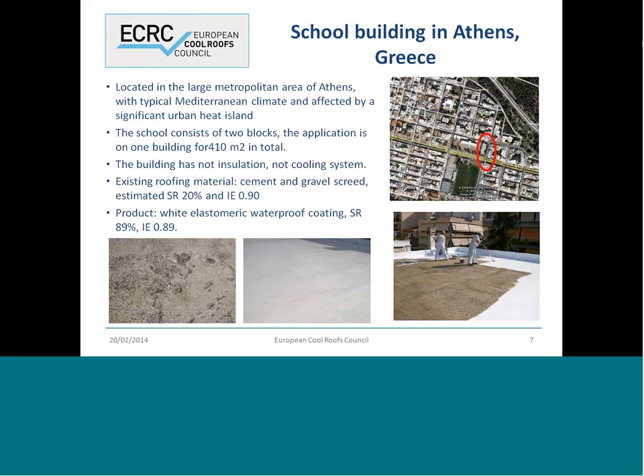This building has no thermal insulation and no cooling system installed. The existing roofing is made of cement and gravel screed with an estimated reflectance of 20% and emissivity of 0.9. The cool roof product is a white elastomeric waterproofing coating with a very high solar reflectance, 89%, and high infrared emissivity. The photos below show a close-up of the 2 materials, the existing one and the cool application, while on the right we can see the works to make such application.